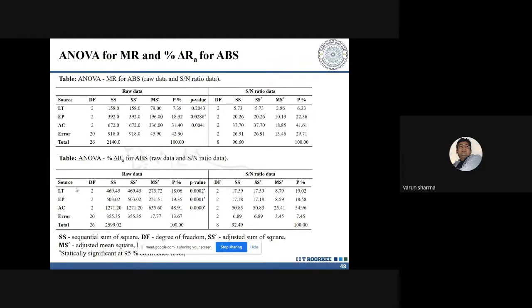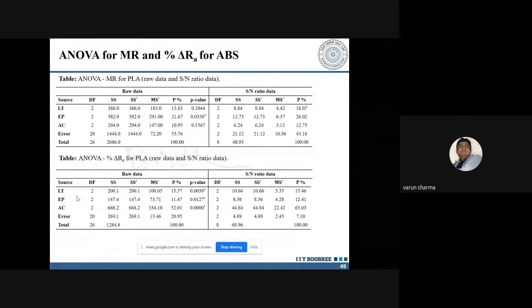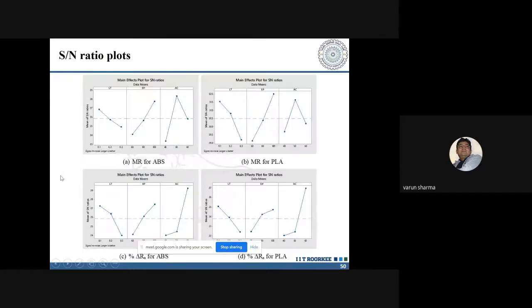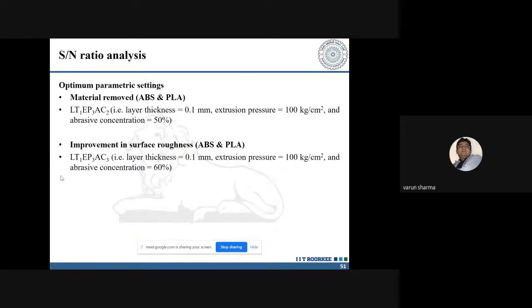For example, in the case of material removal, it is just the extrusion pressure that came out to be significant. In the case of the percentage improvement in del Ra, all three parameters came out to be significant for the ABS. Similarly for the PLA, for material removal it was just the extrusion pressure, and for the percentage del Ra, all three parameters came out to be significant. Now, these are some of the signal to noise ratios for this.